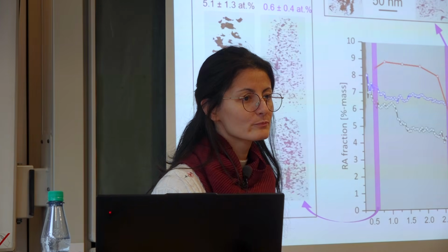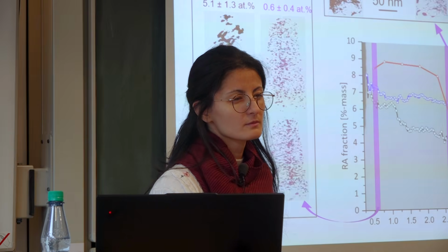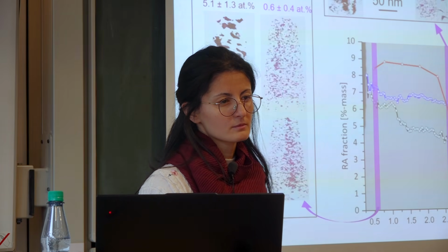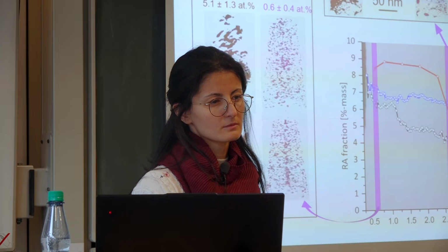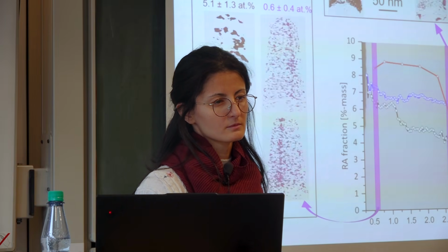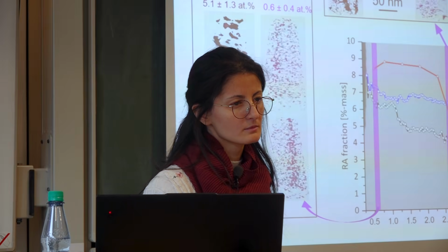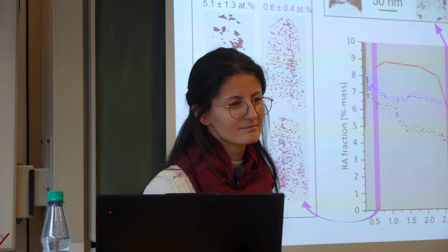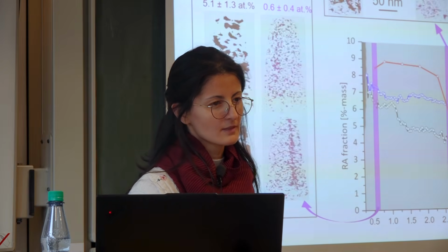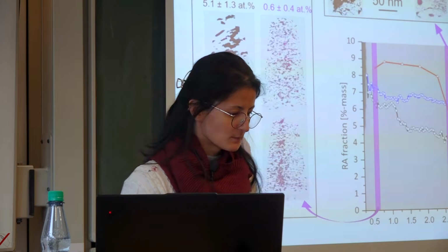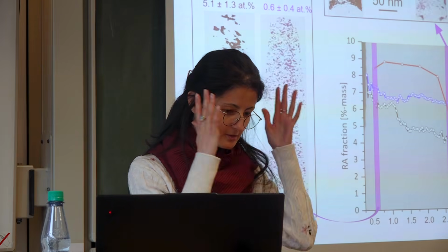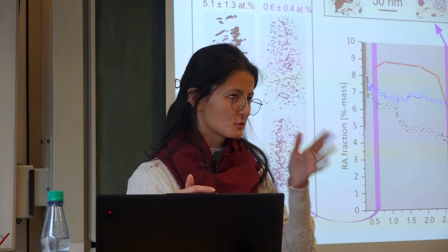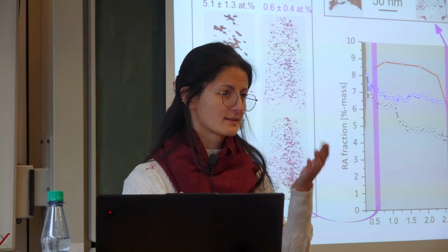To what extent does this technique work for lightweight materials, for example, helium or hydrogen? When you are applying the voltage and the ion is ejected, how efficient is the detector at detecting those lightweight materials? So the detector is constituted of microchannel plates, and 50% of the surface of the detector is covered by this microchannel plate.